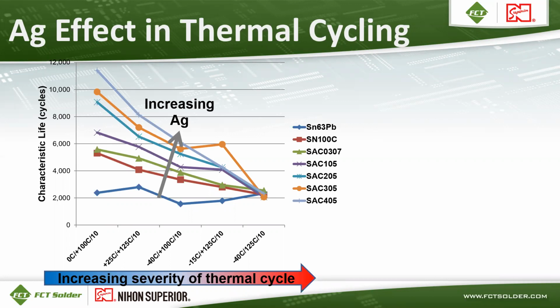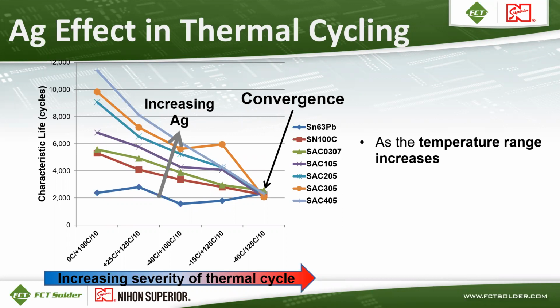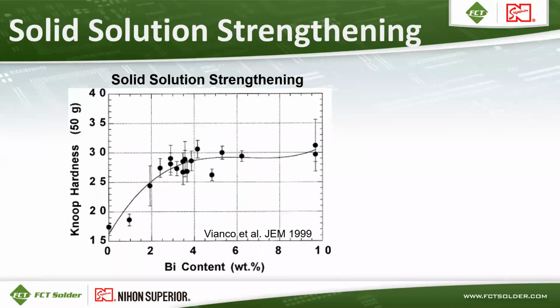So as you go from 0 silver up to 4% silver, the characteristic life is longer with that less aggressive thermal cycle test. But as you go to the more aggressive thermal cycle test of -40 to +125 C, which has become fairly standard in our industry, there's a convergence of characteristic life. So the life is the same for all these alloys under those thermal cycling conditions. So as the temperature range increases, the effect of silver on reliability decreases. So that means that we need alternatives to silver. We need some other elements or additives to these solder alloys in order to withstand those more aggressive thermal cycle tests.